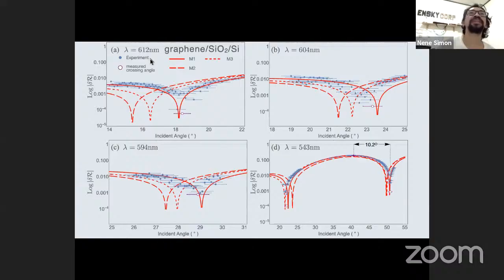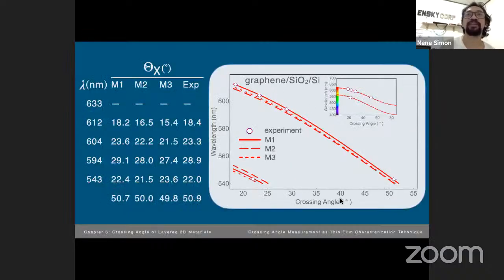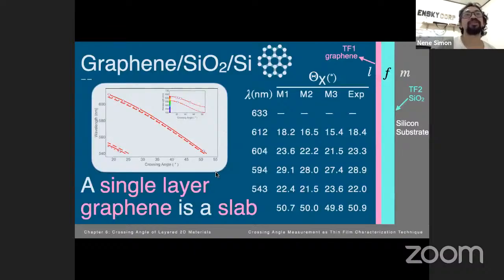I'd like to note that for 633 nanometer incident wavelength, there is no predicted crossing angle, which is verified also in the experiment. So to summarize, I have here my curve of the crossing angle with respect to the wavelength. And as you can see here, 633 is around here. It has no crossing angle. The open purple circles are the positions of the crossing angle. And here's the summary. For all the HeNe wavelengths, M1 predicts the nearest with respect to the experimental measurement. So with this, we can say that a single layer graphene is a slab based on our experiments. So why does it matter? It matters because it means that the fields are continuous through the single layer graphene.